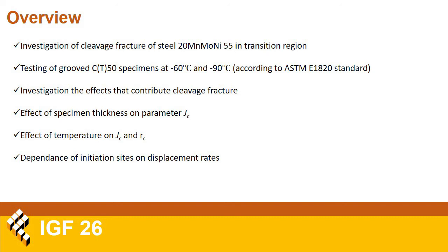cleavage. This aforementioned is discussed by analyzing the parameters that you can see on the slide, to be more accurate their scatter, by testing of CT50 specimens in the transition temperature region at -60 and -90 degrees Celsius. Some of the previous results were added in this study, which will be presented in the further part of this lecture.